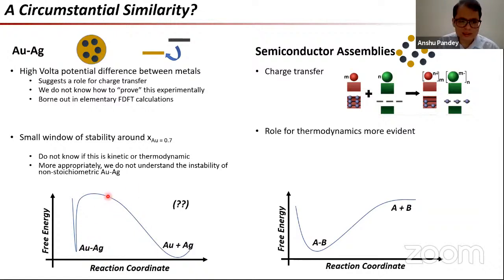If I had to draw a free energy surface, if I'm brave enough to do that, I would draw something like this, where we have around a 0.7 optimum over here. And then this, well, naturally, we do not know its depth. It does not appear it is as stable as gold or silver. Certainly the pure phases are much more stable.